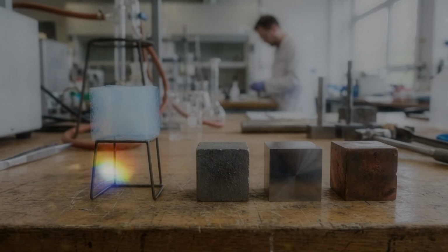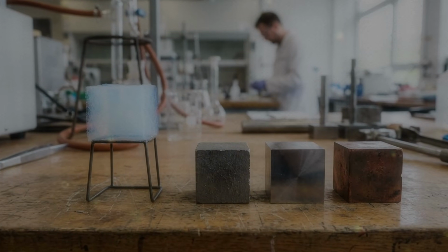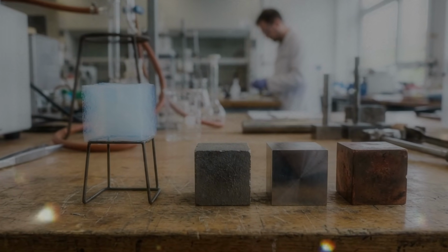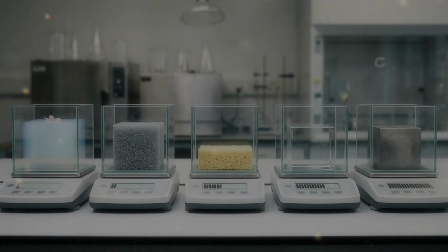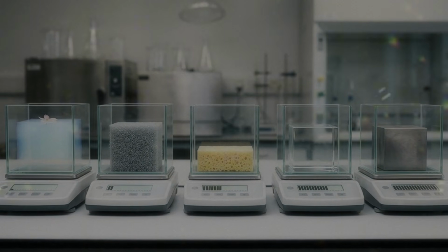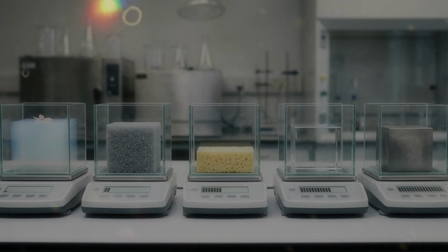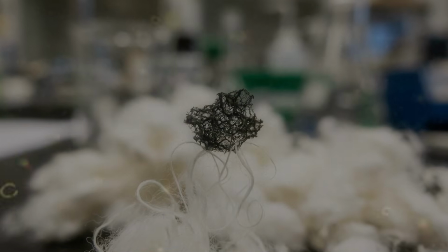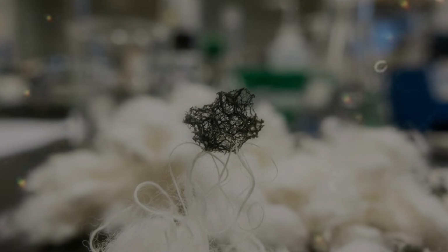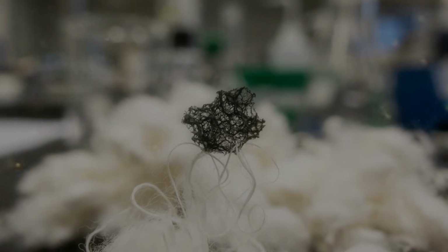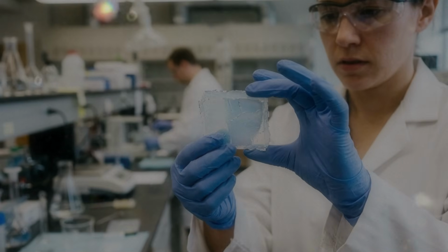Aerogel-based blankets, particles, and layered insulation systems have been tested for tanks and transfer lines. Their tiny pores restrict gas conduction, and their low density limits added mass. Some systems combine aerogel with reflective layers that reduce thermal radiation. Each part handles a different route by which heat tries to enter.